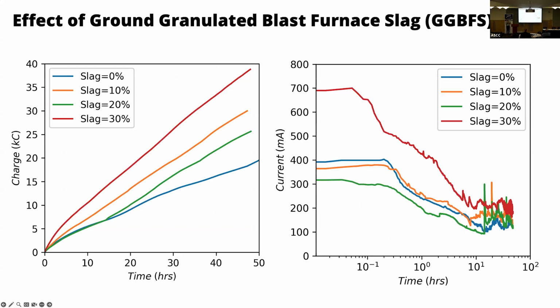Another thing is about the slag use. Nowadays, the importance of low carbon concrete is higher, so a lot of the industry tries to use slag in the concrete. However, here is a little bit of a problem. The electrical conductivity of slag concrete is higher than the normal one. As a result, the risk of corrosion becomes higher, which means that corrosion inside of slag concrete is going to be faster. So that would be a problem.